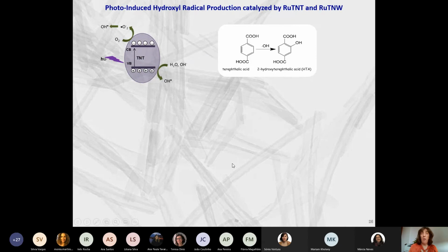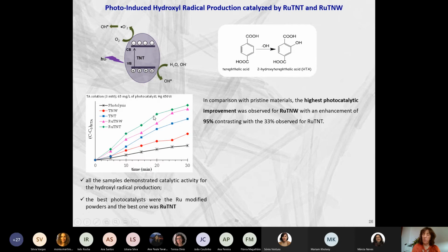After that, we have the materials characterization finished, so we need to start to study the photocatalytic performance of these materials. Usually, we start with the terephthalic acid. Why? Because it's a model molecule that degrades via hydroxyl radical, producing this species. And we are able, using fluorescence spectroscopy, to detect this molecule, this species.